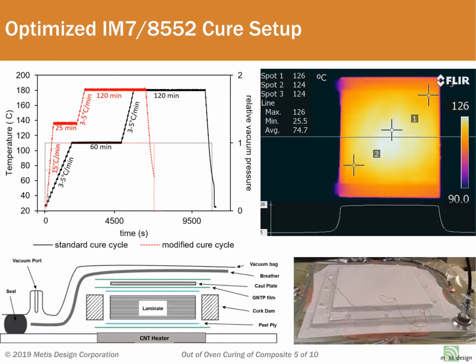In addition to the energy savings, we have also demonstrated as much as a 40% reduction in cure cycle time, which would further reduce overall energy consumption, as well as reducing the component fabrication cost directly. This can be achieved by accelerating the temperature ramp rates using CNT heaters and eliminating much of the time it takes for heat to get to the surface of the laminate. Once the laminate surface is heated to the desired temperature, the cure process is the same whether heating convectively or conductively, as it just reduces to a simple 1D thermodynamic problem.